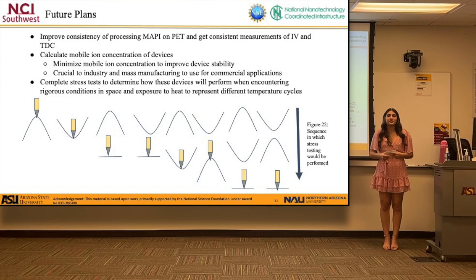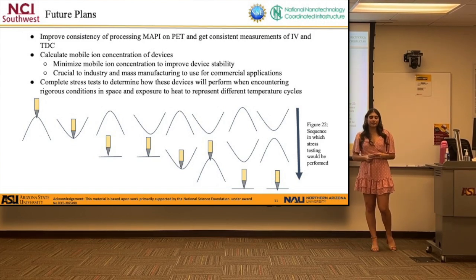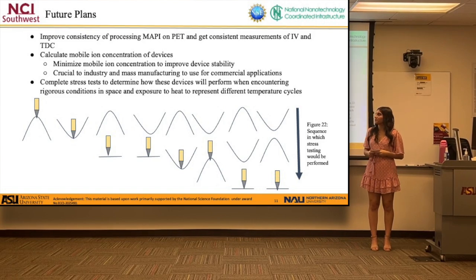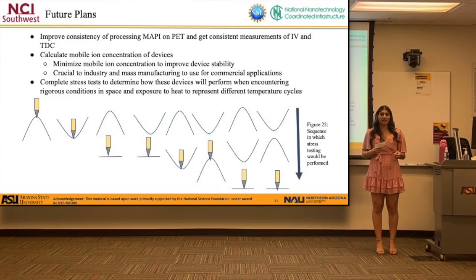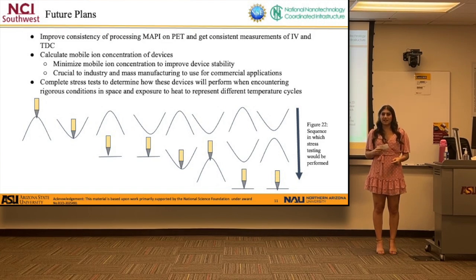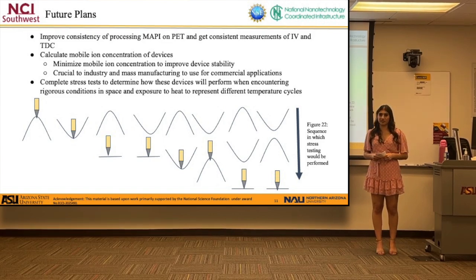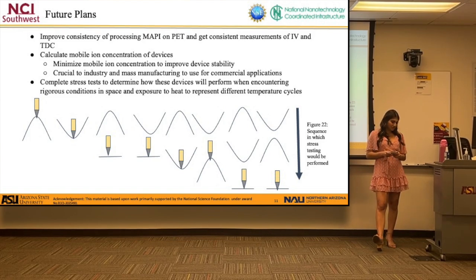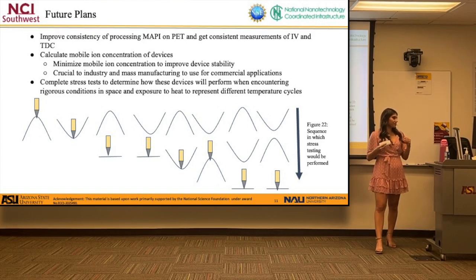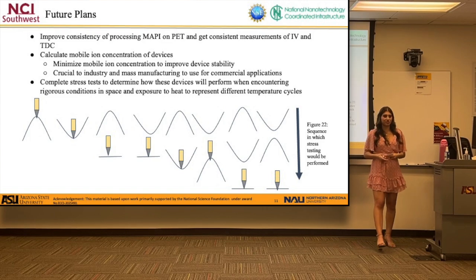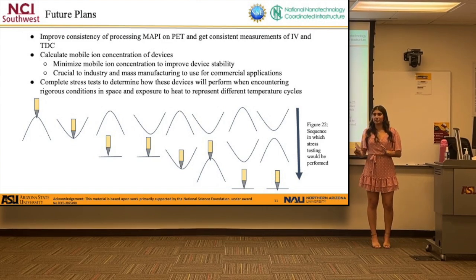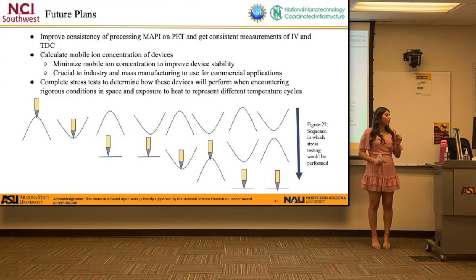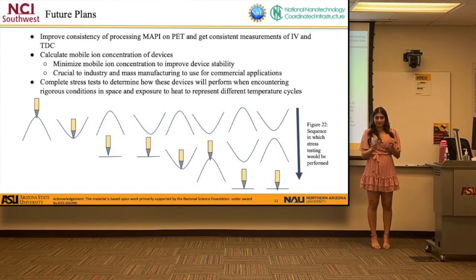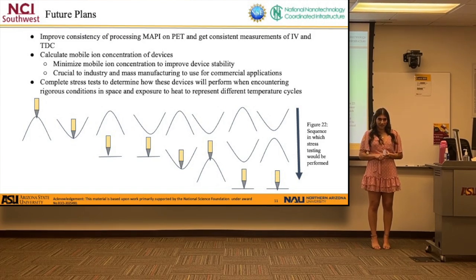As far as my future plans, I really want to improve the consistency of the fabrication process of the MAPI perovskite on the PET. I really want to get consistent measurements, the IV measurements, and the transient dark current measurements, as well as I want to continue calculating the mobile ion concentration. Now, the relevance of this is that it's crucial to industry and mass manufacturing for commercial applications. I eventually want to minimize the mobile ion concentration because minimal ion concentration minimizes the degradation of these samples.